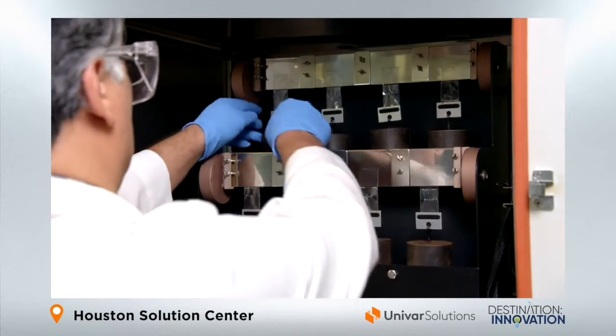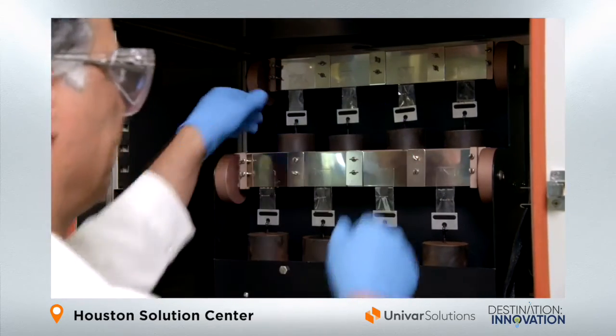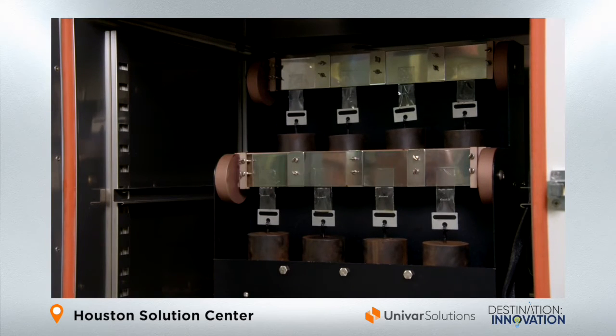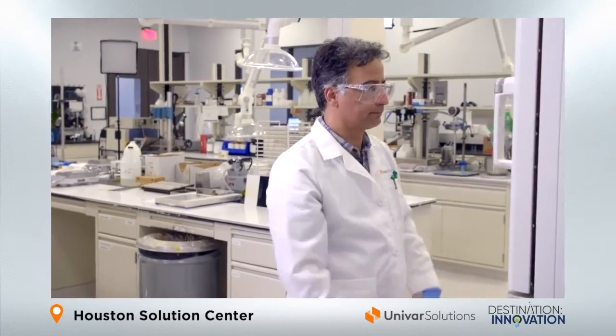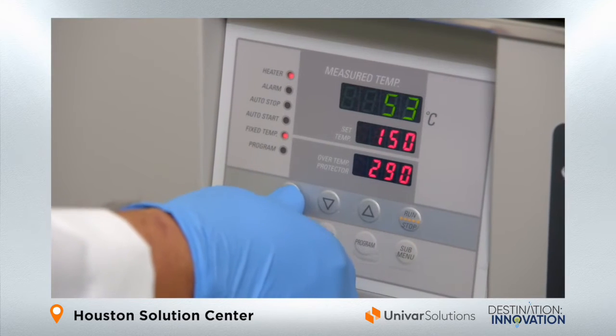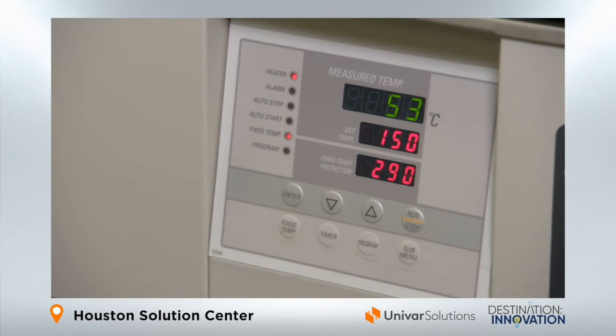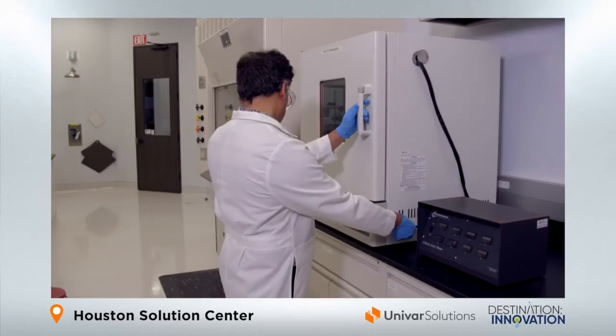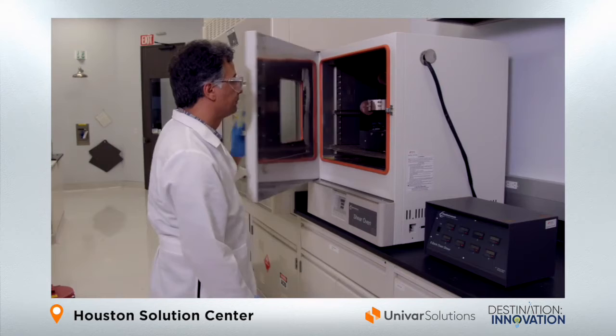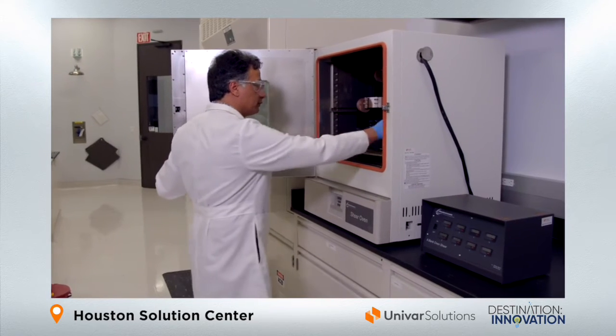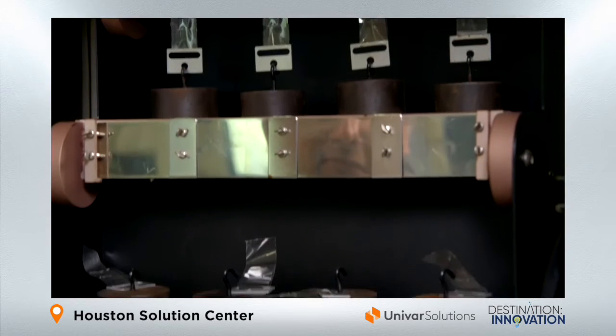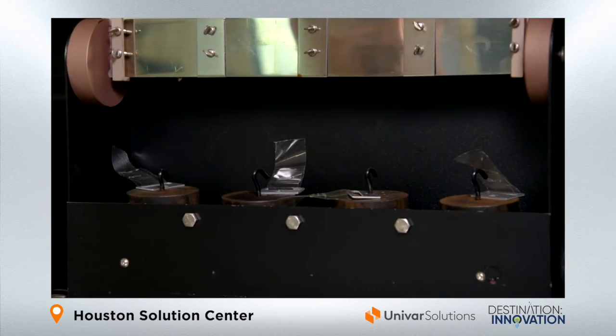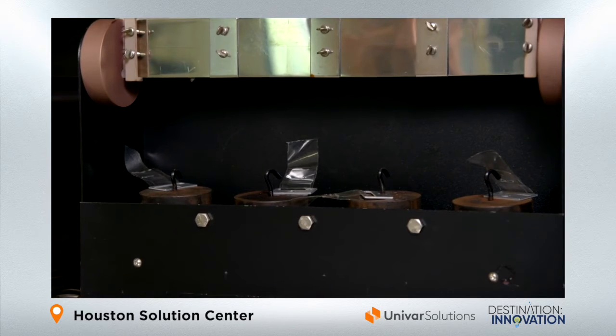This second test is showcasing shear adhesion failure temperature. Multiple specimens are applied to mylar and adhered to polished stainless steel, then hung under weight in a temperature-controlled chamber, the shear oven. The weight applied is uniformly 1 kilogram for all specimens. The temperature in this case was set to 150 degrees Celsius under static control parameters. However, we have the ability to run this test in many different modes. Through utilization of the timer system, temperature can be manipulated dynamically. Also, failure can be recorded automatically based on time and current temperature, as there are pressure sensors in the chamber that register the weight contacting the bottom.